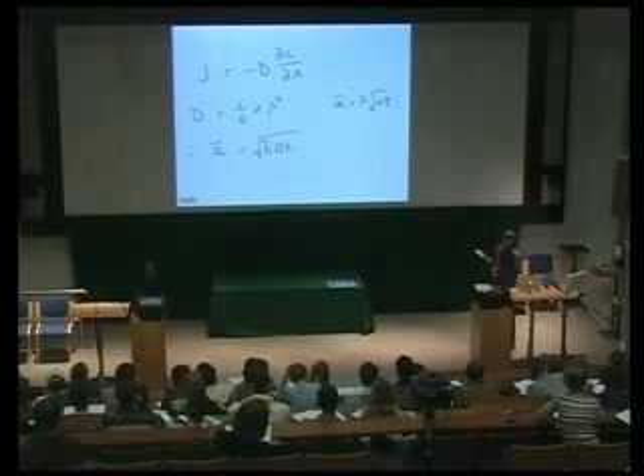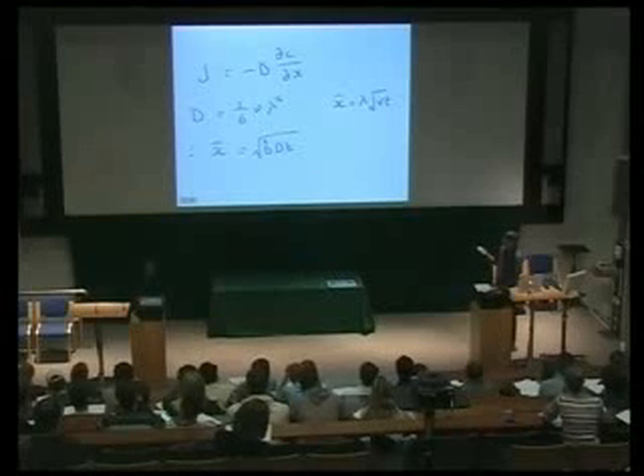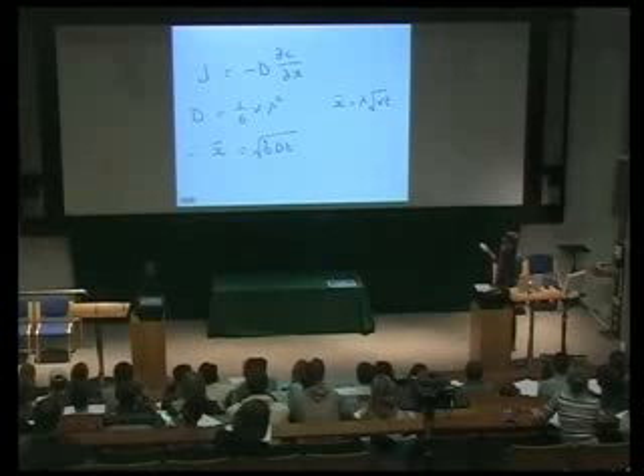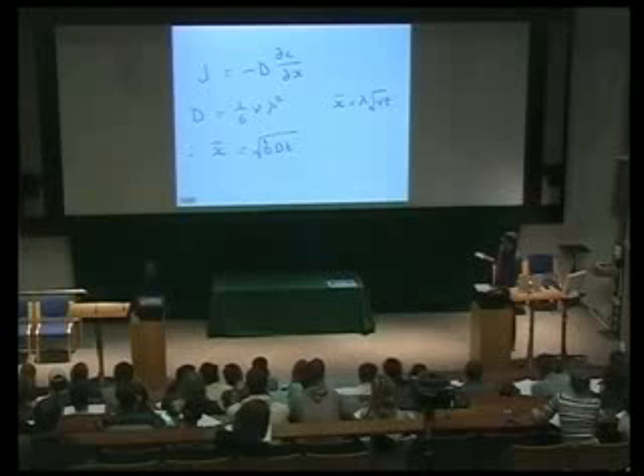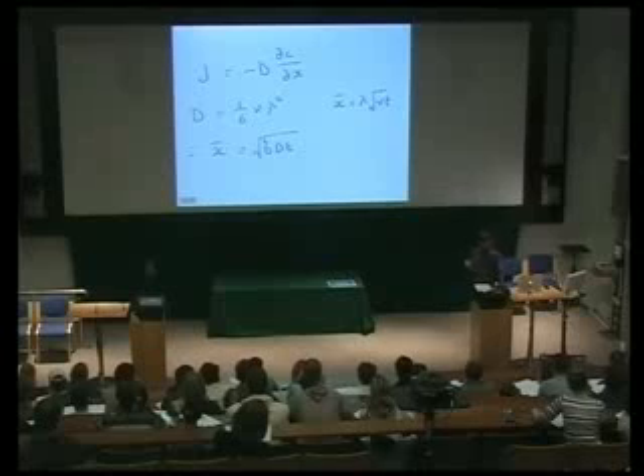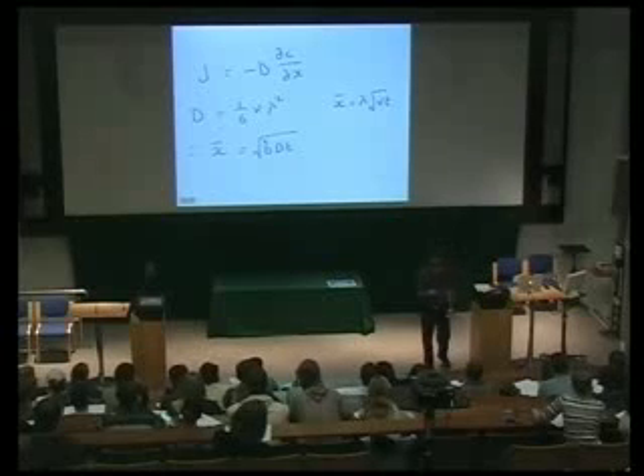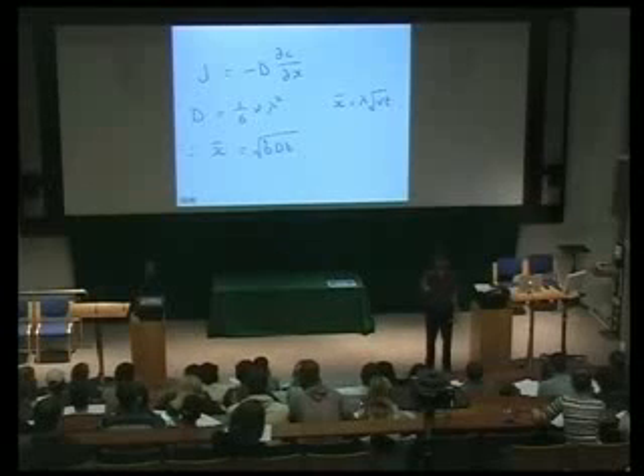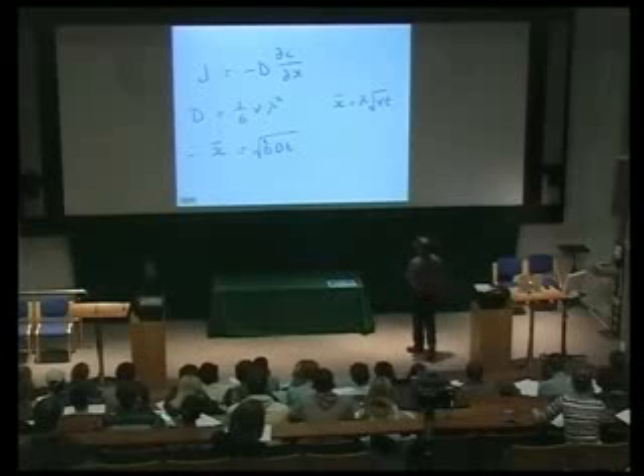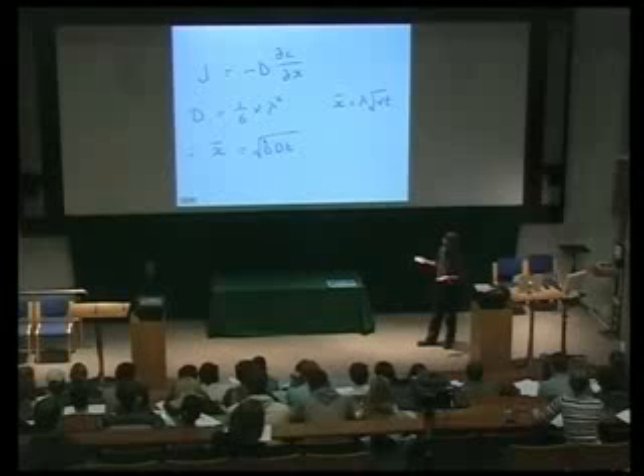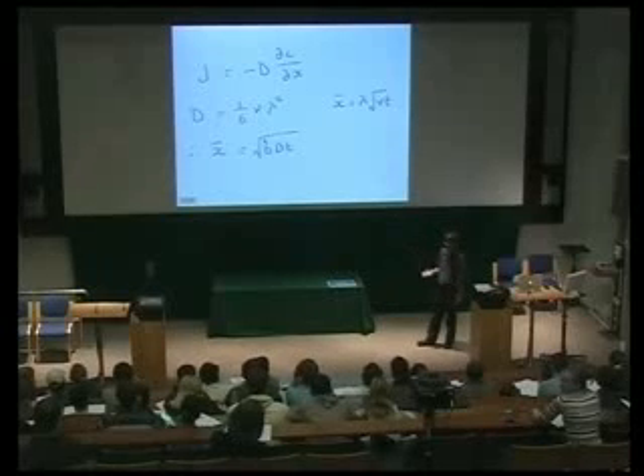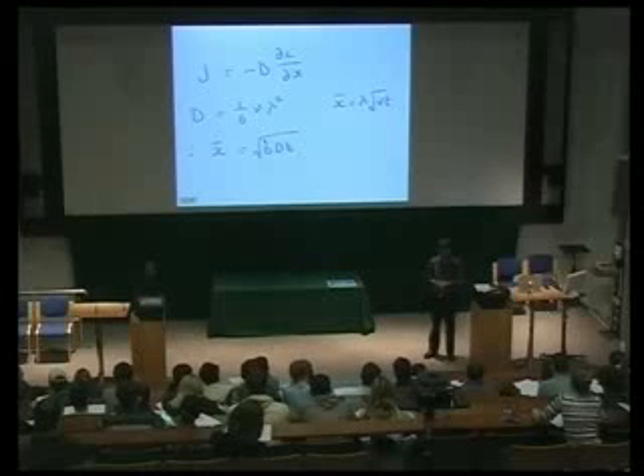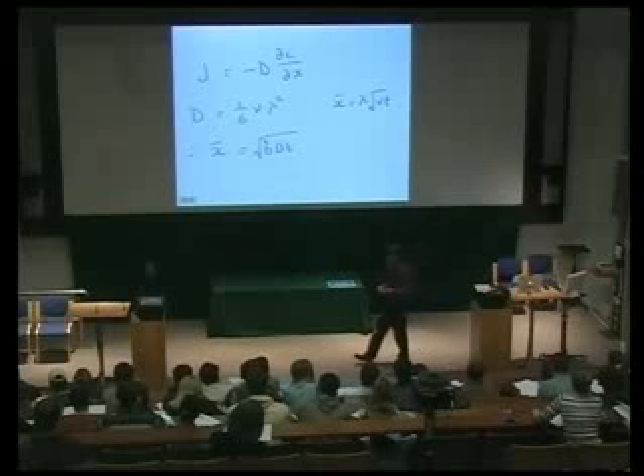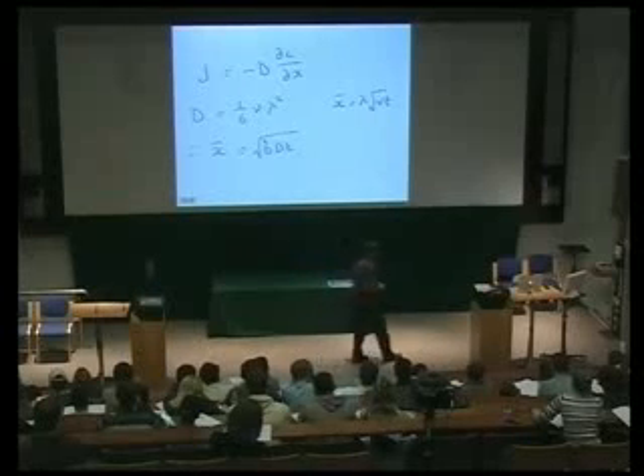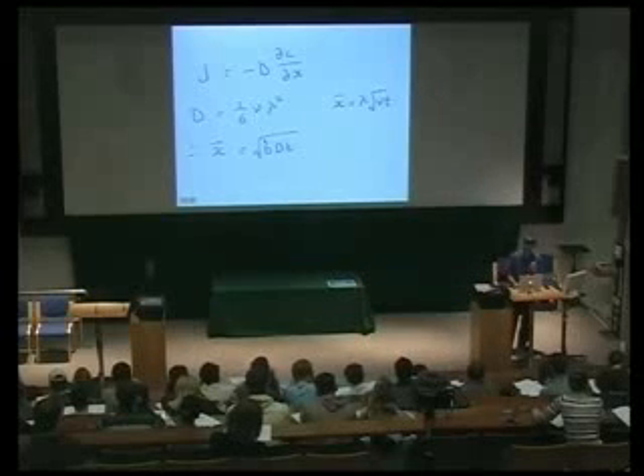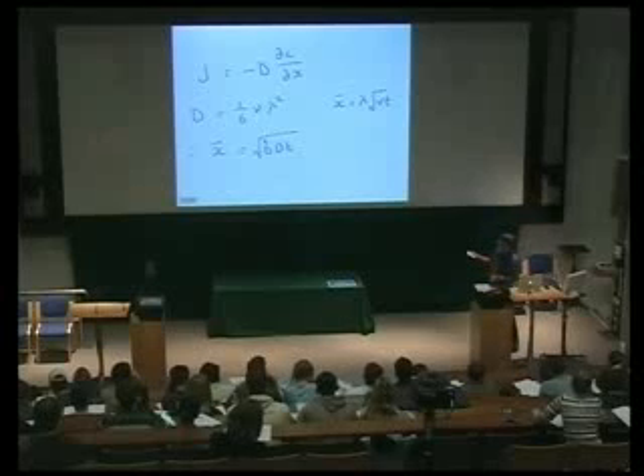Now we know from the random walk analysis that the root mean squared jump distance is proportional to the square root of time, the square root of frequency, and the jump distance lambda. So if I substitute in here, you can estimate a rough diffusion distance if you know the diffusion coefficient. Okay? So you can find collections of diffusion coefficients in data books. And if you want to work out the rough distance that an atom might diffuse in a time t, then you simply say it's root 6 dt. Okay? So that's a very good way of working out a rough diffusion distance. An order of magnitude approximation, because we haven't got any gradients, etc. in here. Okay?